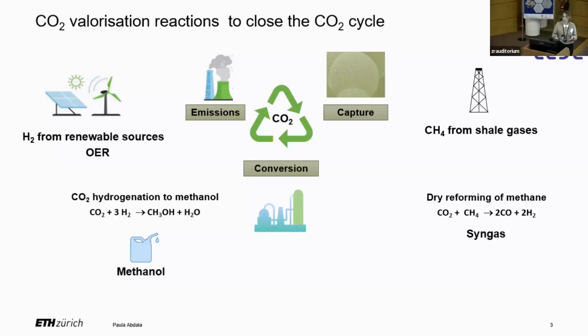And this adds cost to the processes, but we can add value to carbon dioxide by converting it into useful feedstock. And we can do this via catalytic process. For example, we can convert carbon dioxide via the reaction with hydrogen, green hydrogen, and produce methanol, which is an important chemical and fuel. Another process that we work on is the dry reforming of methane that allows us to react methane and CO2, two major greenhouse gases, to produce syngas, a mixture of CO and hydrogen that can be used in other processes.